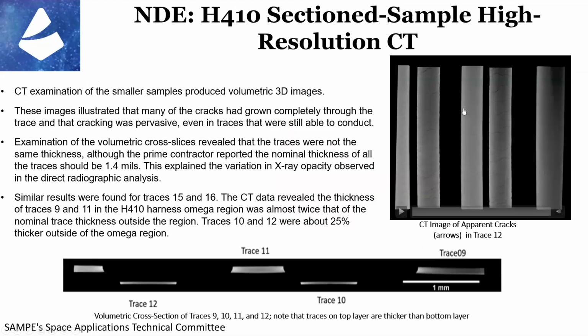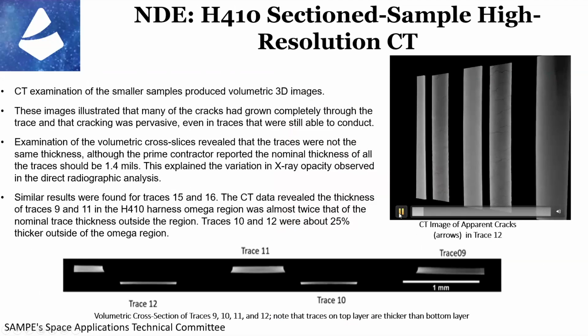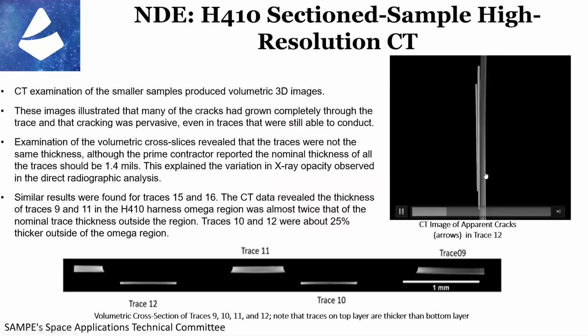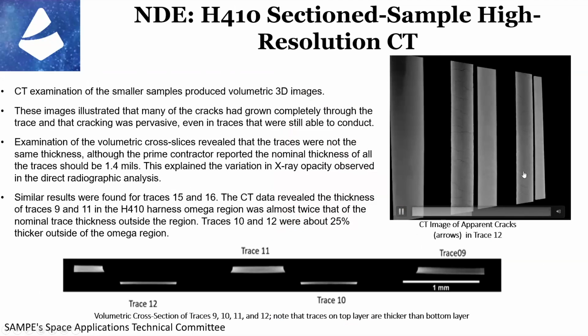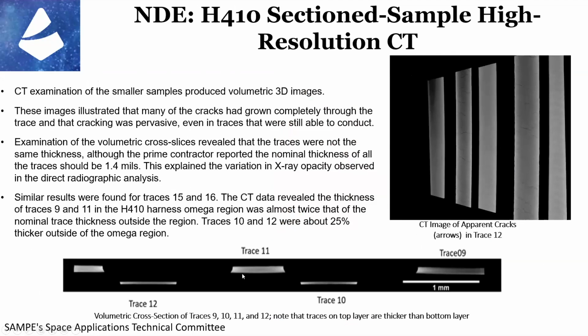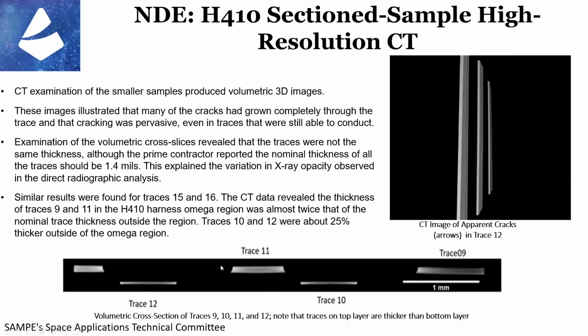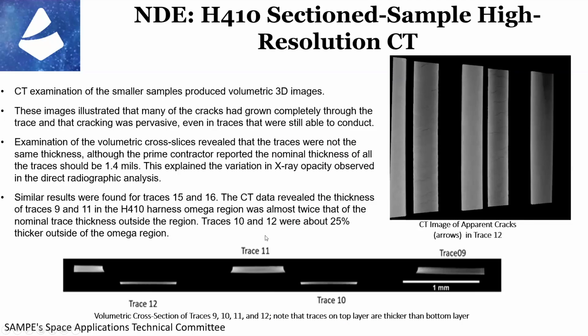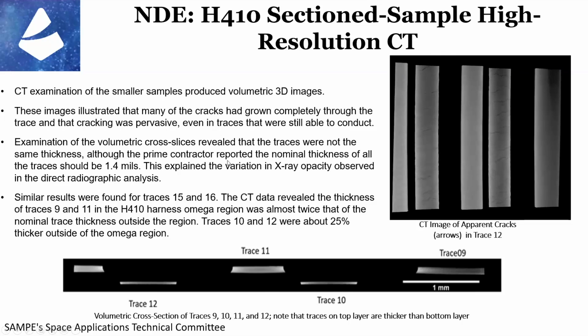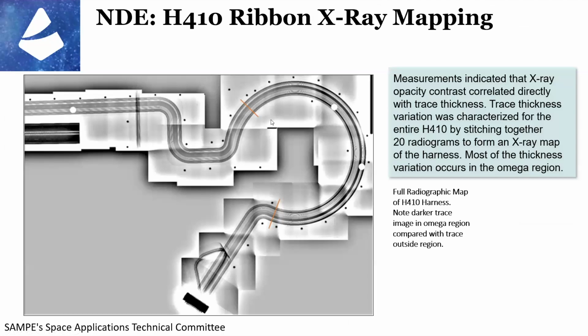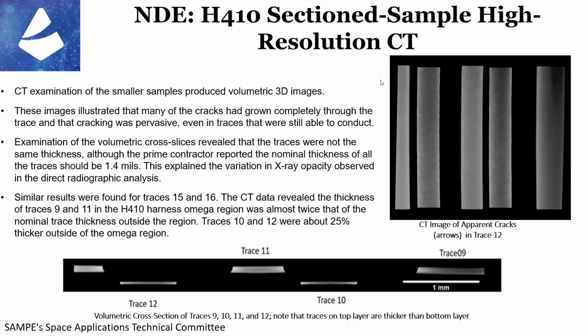So I don't know if this one, yeah. So got a nice little, so probably easier to see. The cracking is definitely all on one side of the harness. And what we ended up noticing from the CT is that one set of the wires was a lot thicker on one side than on the other, by about 25%. And that's what actually led to the root cause of the problem, is that it created sort of an I-beam effect that's on the last slide.